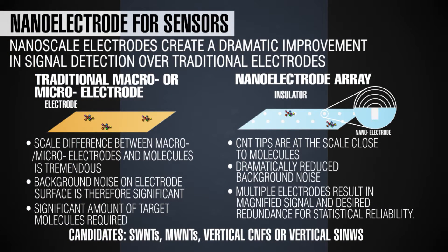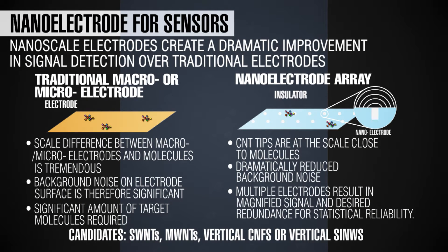If you have a 50 nanometer diameter electrode, a back-of-the-envelope calculation tells you the neighboring electrode should be at least 1.2 to 1.5 microns away to avoid overlap of the two radial diffusion layers. To accomplish well-separated individual nano-electrodes, one can use carbon nanofibers — these are multi-wall carbon nanotubes that are individual freestanding nanostructures. Other choices include vertical silicon nanowires or vertical zinc oxide nanowires — any of these can be used to create a nano-electrode array.